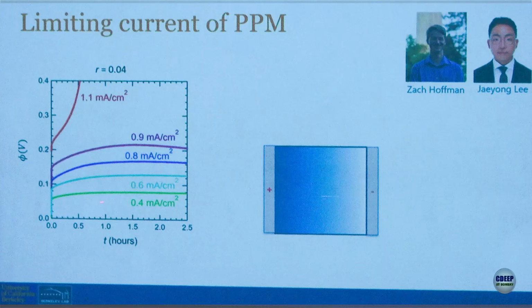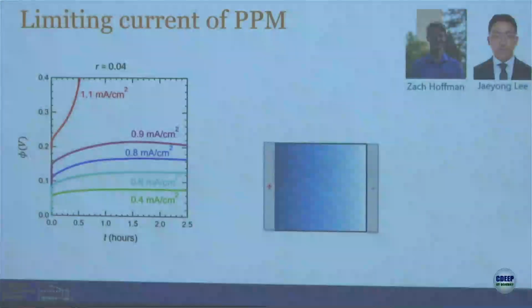And all of us sort of protect our batteries, and we stop the current. We stop when the voltage reaches some sort of cutoff. So there's a clear divergence between this current density and that current density. And I would say that the critical current, or the limiting current, sorry, is 1 in this case, 1 milliamp per centimeter squared.